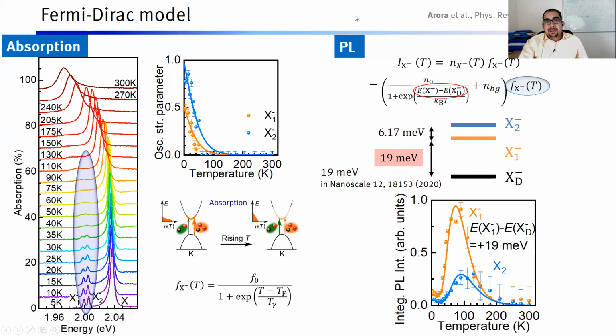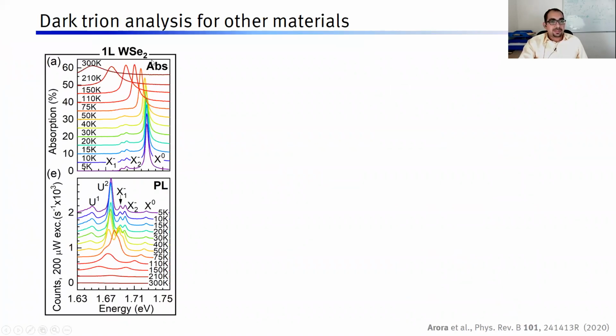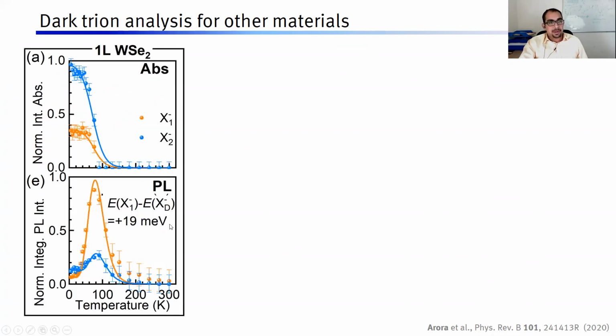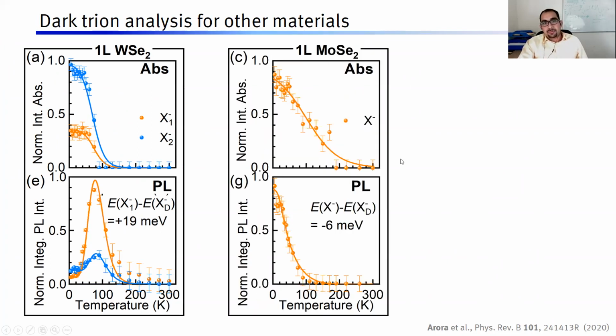In fact, this has been verified in another work where they measured the dark trions with some specific method by applying large magnetic field. Directly they measured the energy and they find it is correct. It's 19 meV. So it's exactly the same. Finally, we do the same thing for other materials. For example, for tungsten diselenide, we find that everything works with 19 meV below. For MoSe2, we find everything works with 6 meV above now. So the bottommost state for MoSe2 is a bright state by 6 meV and the dark state is above.